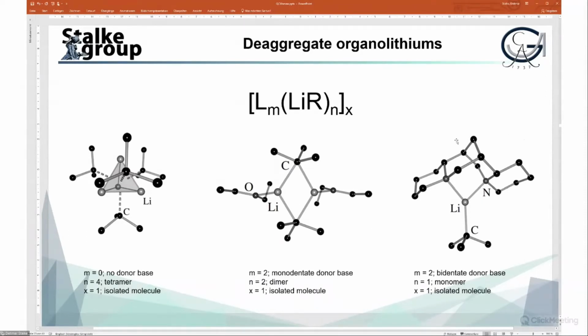If you add a chelating donor base like sparteine, my dear colleague Carsten Strohmann isolated this monomer where he had only 1 lithium-carbon contact, and this material is, as you can envisage, basic as hell. So this is a really reactive motif in lithium chemistry.